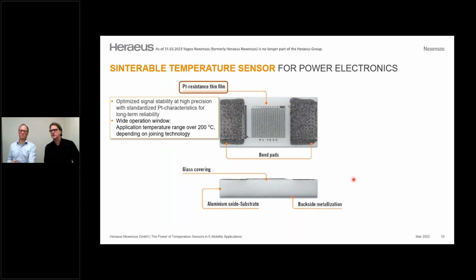We have different functional areas in the middle. What is highlighted here, you see the meandration, which is a platinum resistance thin film. And this is optimized for a very stable signal over a long period of time. And the operation window is for that meandration only on a substrate like aluminum oxide or glass or something like that, up to 1000 degrees. In our application here for the power electronics, it works quite well, also over 200 degrees. The limitation is on the other side. That means, please, the next step.